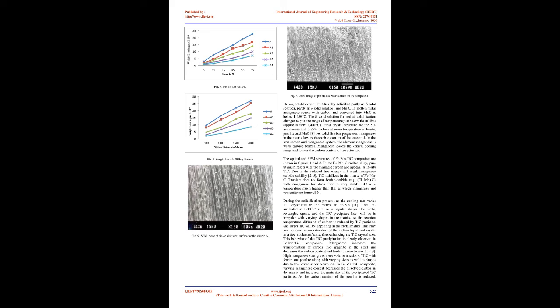During solidification, Fe-Mn alloy solidifies partly as delta solid solution, partly as gamma solid solution, and Mn3C. In molten metal, manganese reacts with carbon and is converted into Mn3C at below 1450 degrees Celsius. The delta solid solution formed at solidification changes to gamma in the range of temperature just below the solidus, approximately 1400 degrees Celsius. The final crystal structure for the 5% manganese and 0.85% carbon at room temperature is ferrite, pearlite, and Mn3C. As solidification progresses, manganese in the matrix lowers the carbon content of the eutectoid.